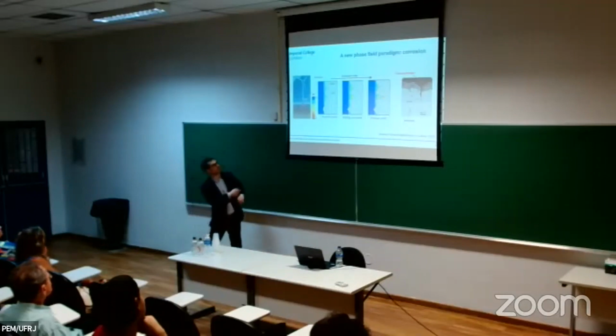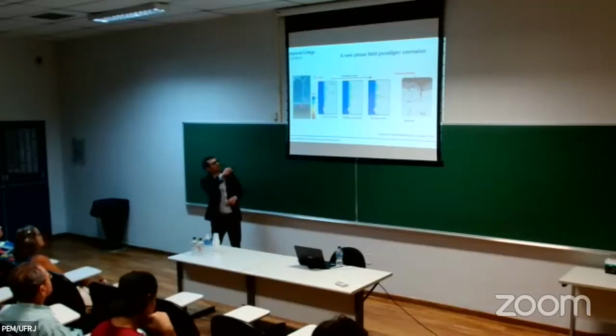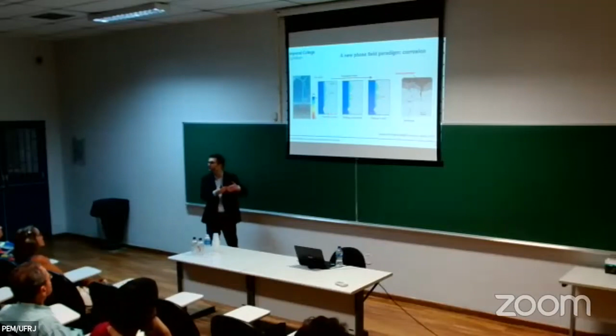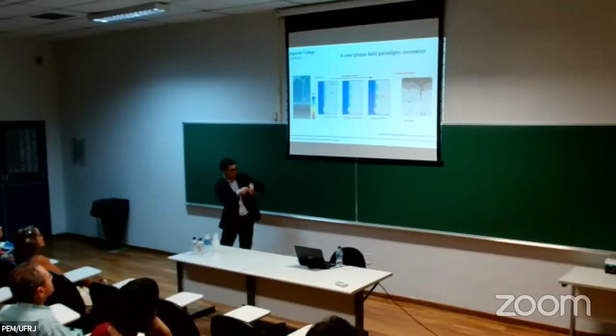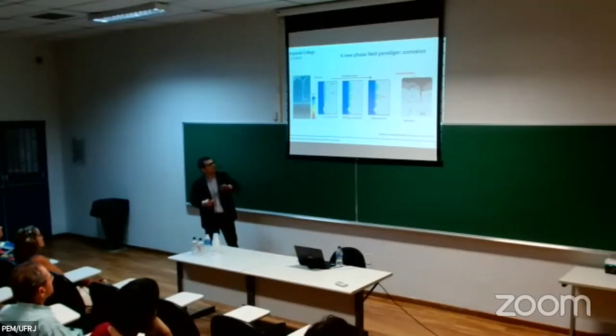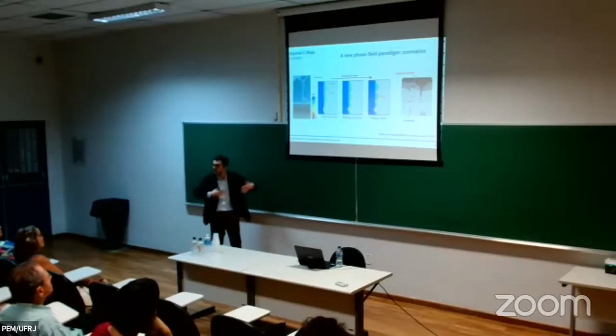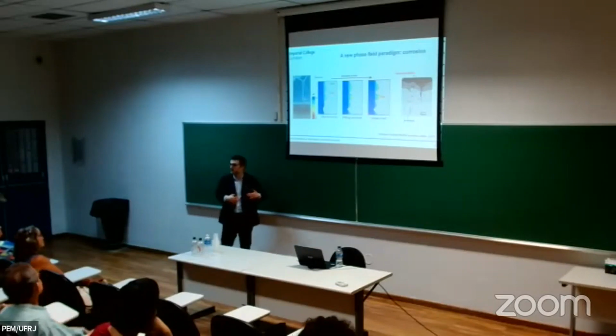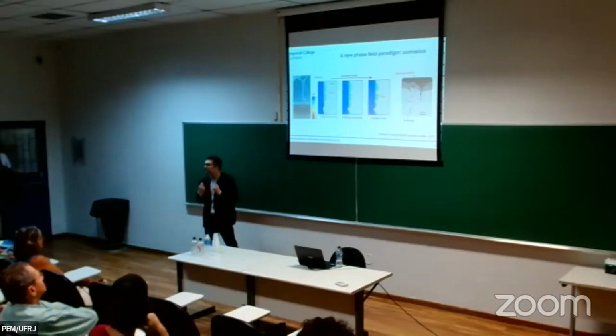But it's quite complicated. As you see, first you get pits and nuclei at the interface between the aqueous electrolyte, the seawater, and the metal. Those pits grow, driven by local chemistry and mechanics, and eventually you get this kind of pit-to-crack transition event and the propagation of fatigue cracks. So the key thing is that, first of all, you need to be able to capture a very complex morphology. Because the corrosion has a very fine shape, you need to capture how it evolves. And second, it's a very strongly coupled problem.